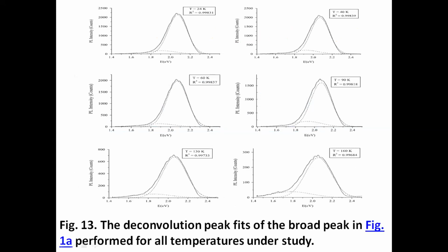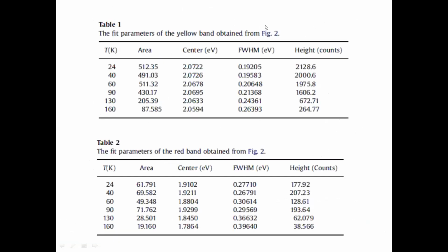Now, a deconvolution peak fit was made at every temperature for the first peak, which includes the yellow and the red bands. It was deconvoluted into two peaks. One represents the yellow band and the other represents the red band. It is done for all temperatures. The fit parameters are inserted in these tables: this table for the yellow band and this table for the red band. It includes integrated area under the peak, center, full width at half maximum, and height.